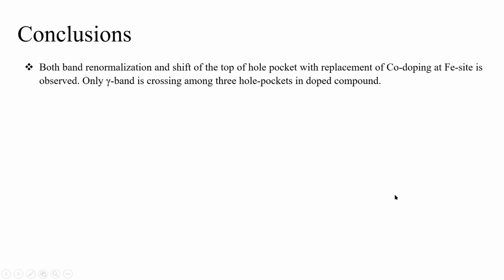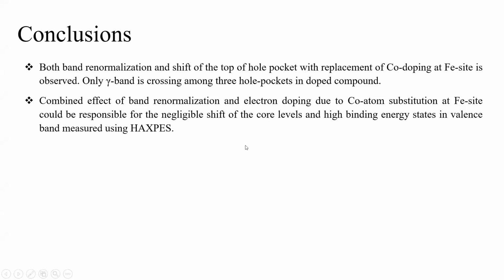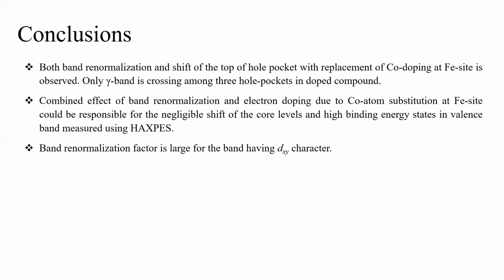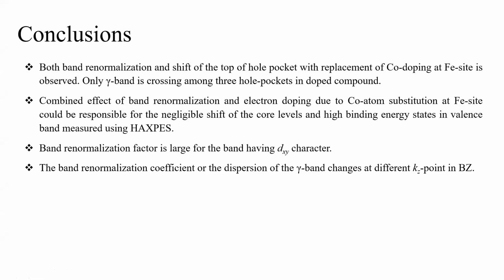First I gave some brief discussion on the iron superconductors. In the last 4 or 5 slides, I discussed the effect of cobalt doping at the iron site, and we measured significant band renormalization and a shift of the top of the hole pocket with cobalt doping. We also observed that only the gamma band is crossing the Fermi energy among the other three bands which were crossing the Fermi energy in the parent compound. The negligible shift of the valence band and core levels that we observed using HAXPES is because of the combined effect of the band renormalization and the electron doping due to cobalt substitution at the iron site, which we confirmed using the RPES study by comparing the RPES spectra of both compounds.